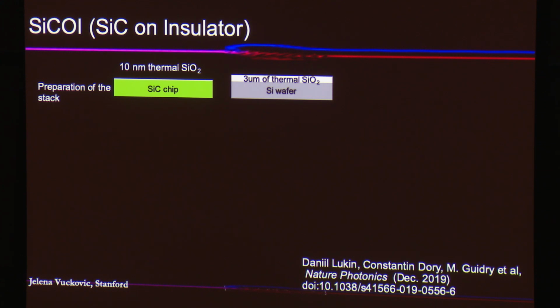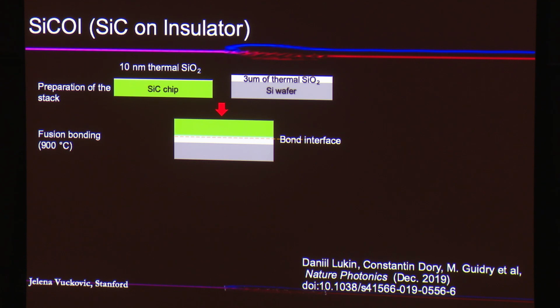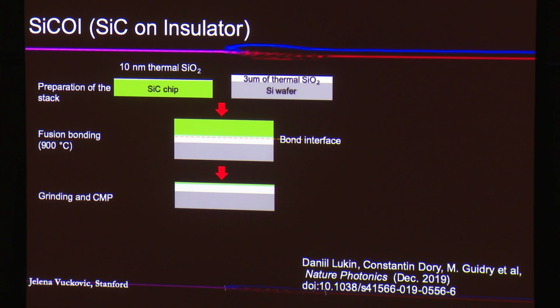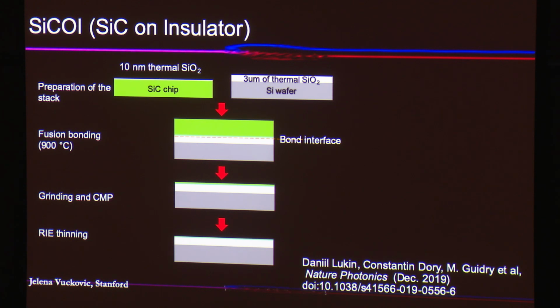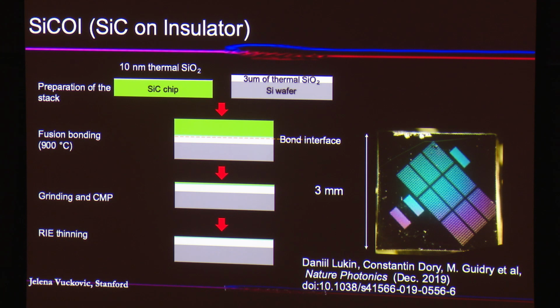And it's very simple. We start from silicon carbide, then we oxidize a silicon wafer, fusion bond the silicon carbide onto the oxidized silicon, and then grind, chemical mechanical polish the wafer, and finally reactive ion etching for thinning at the end. So it's a very simple process, but there is no ion bombardment. You don't damage your silicon carbide wafer. And we can produce few-millimeter by few-millimeter chips, which are pretty uniform, to make photonics.